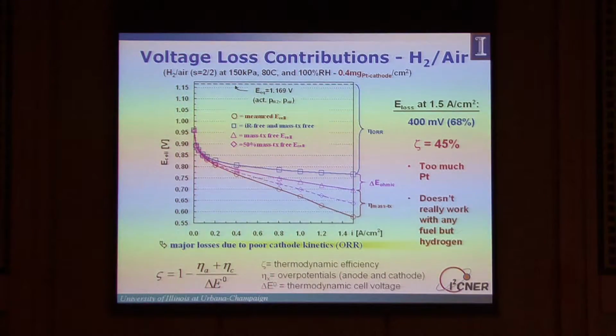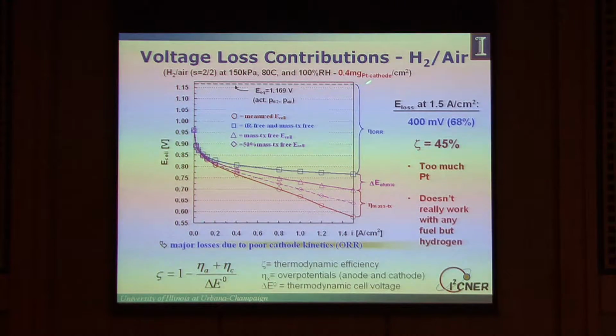It's actually substantially less. Now, as good chemists, we know that if the rate of a reaction is slow, if the number of turnovers per site per second is slow, all we need to do is add more sites. In this case, unfortunately, those sites are made from platinum or one of its alloys. And so maybe you've heard things like there's going to be $5,000 worth of platinum on the vehicle or $10,000 worth of platinum on the vehicle. I think you can choose any number you want because you will be correct as the price of platinum increases without bound. But one of the problems is that the platinum loading, particularly for this oxygen reduction reaction, is very high. And so we want to get rid of that.